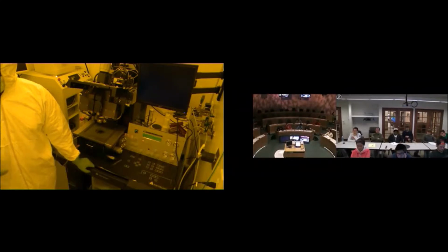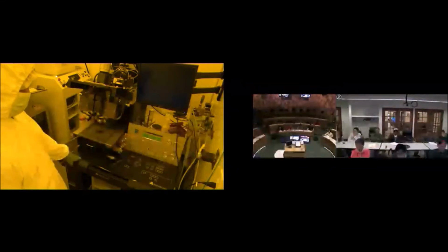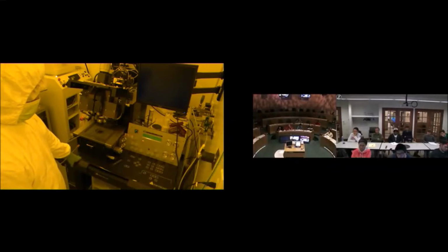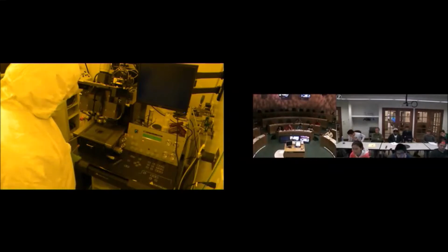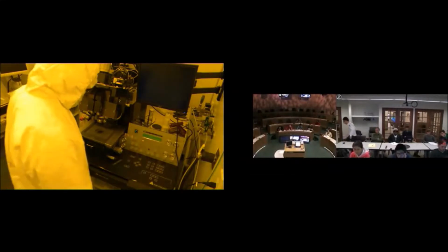And that's something that we have to routinely calibrate. We got to check the photoresist, how much energy does it need to expose. This is about 300, 250 to 300. So since I'm running at 20, I'm going to do an exposure. I can adjust the time. So I'll put it to 15 seconds. That'll give me 300 millijoules. Okay. And I don't need to align. I'll show you the alignment step during the next one.